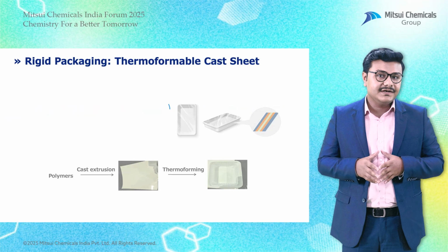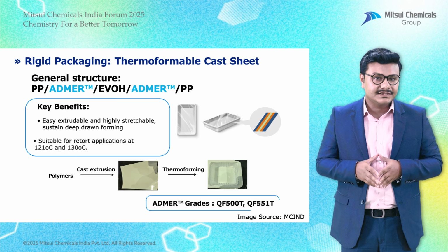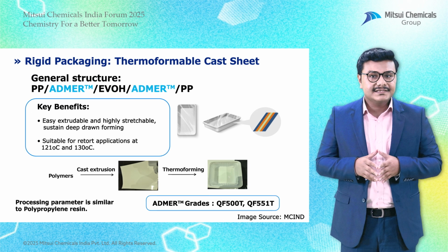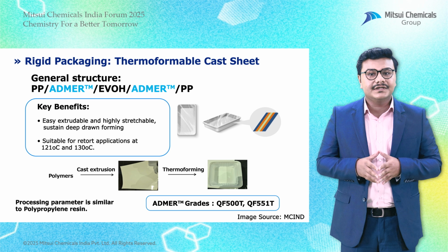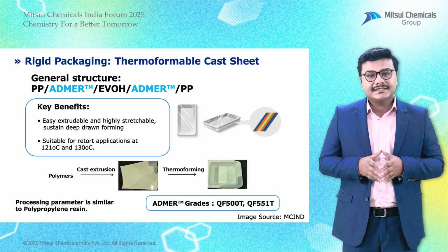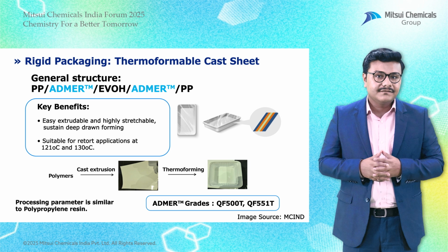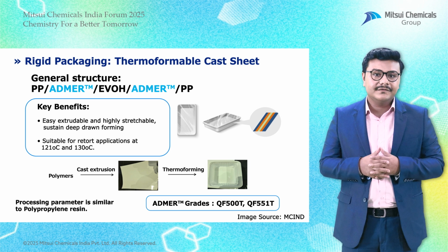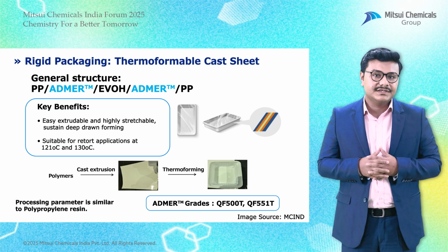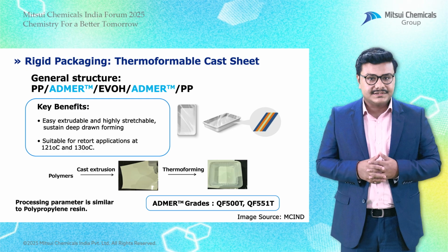Here, Admer is well established for multilayer cast sheet. It is useful as tie resin between EVOH or nylon in structures. It gives excellent interlayer adhesion while extrusion and sustained stretching while thermoforming. It is suitable for deep drawn trays and also sustains high retort temperature process.